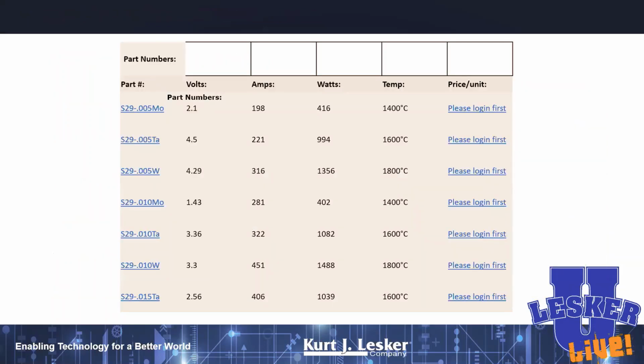I mentioned that the voltage and the amperage that your power supply can generate completely dictates the suite of materials that you can make by thermal evaporation. So if we look at this first item here, and I think this is a screenshot out of our catalog or the RD Mathis catalog, this is a 5/1000th of an inch thick molybdenum boat. And just notice that if I give it 2.1 volts and 198 amps, this thing will go to 1400 C. How clever is that? So if we think back about our example of aluminum oxide, remember that wanted 1550 C in order to give us the equilibrium vapor pressure that we wanted. So 1400 C is not going to do it.